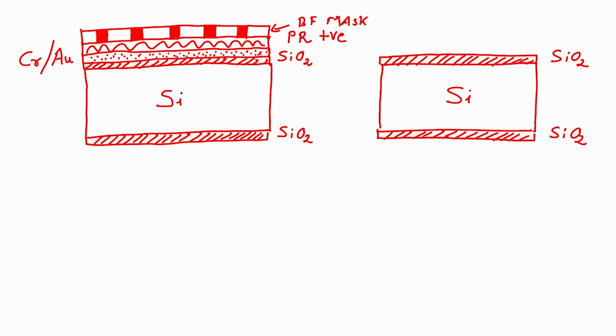Right. Let me write B clearly, bright field mask, correct. This much was easy. Then what we missed: after we spin coat photoresist, we have to pre-bake it at 90 degrees centigrade for 1 minute, right.